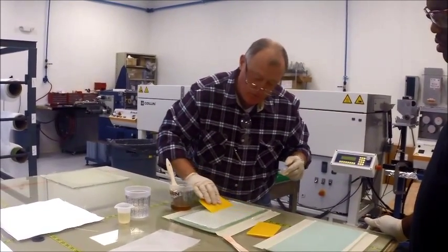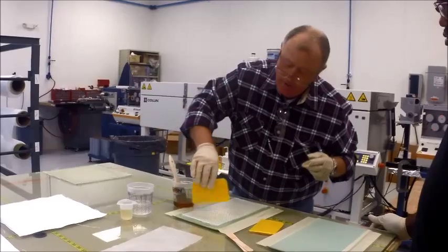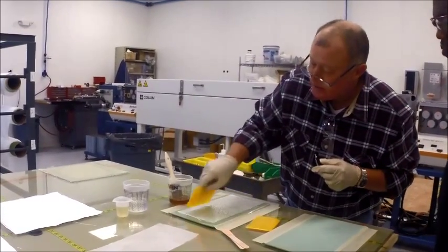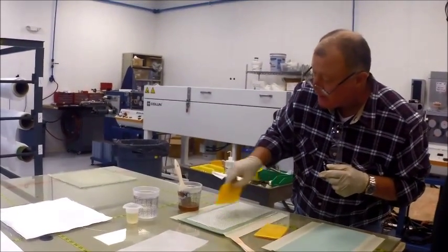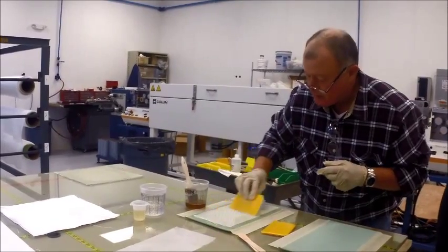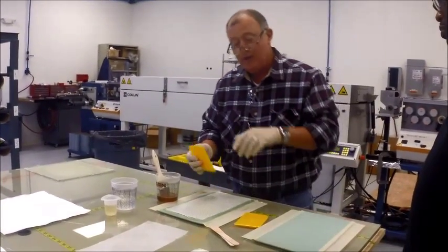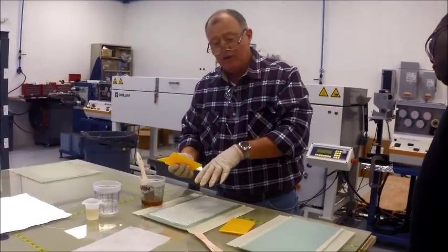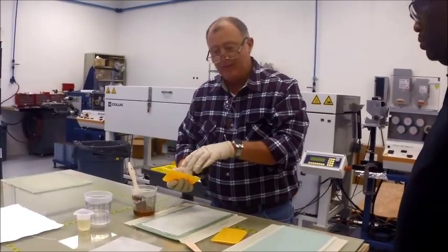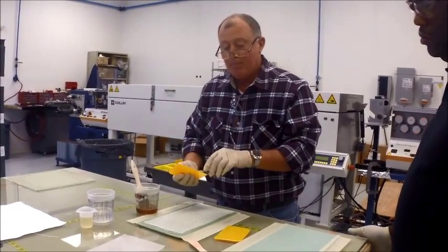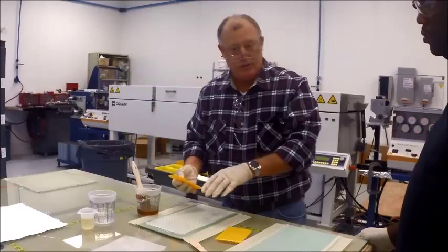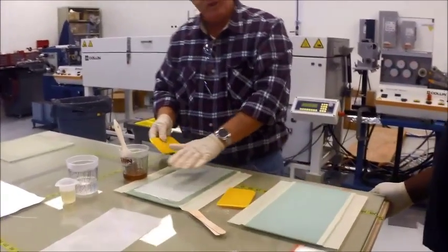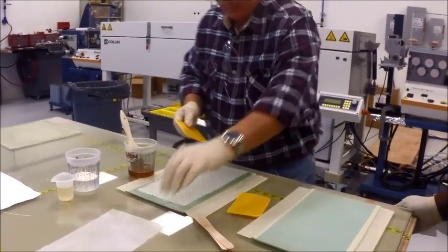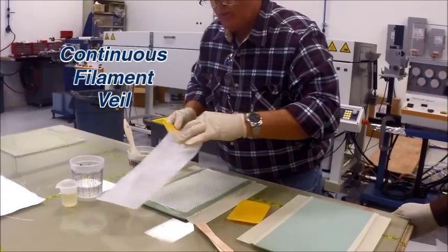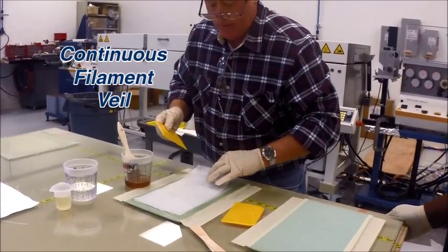Now in this case, we don't want to press too hard because we're not trying to push the resin through the Innegra into the core. We've already done that. What we're trying to do is make sure that we have a good bond between the Innegra and the veil that we put down against the core. So it's okay to have a little extra resin on this particular part. And then last is we'll go on with another veil.